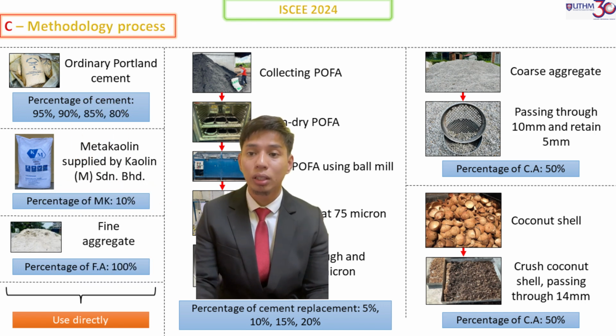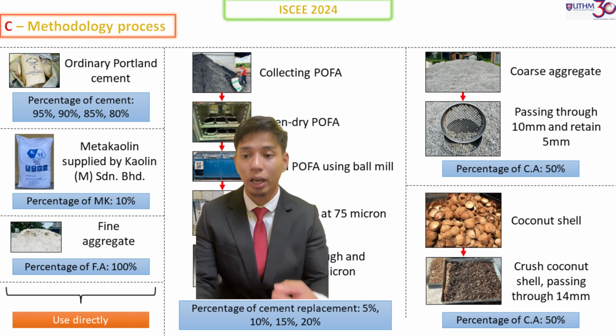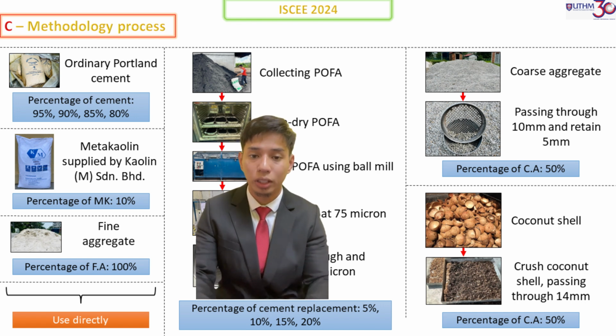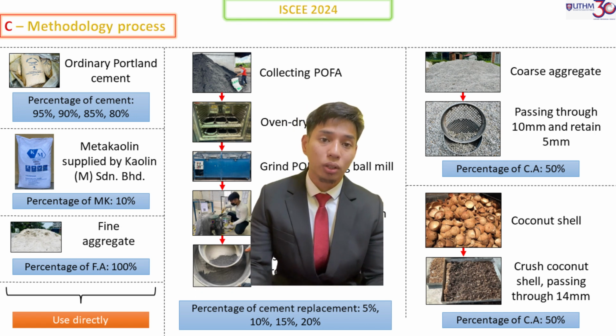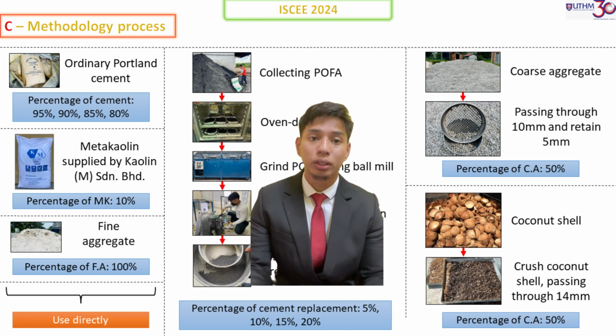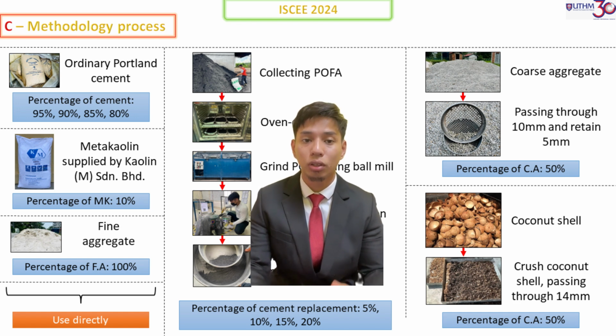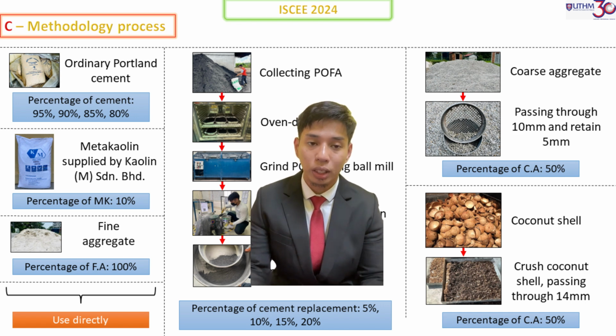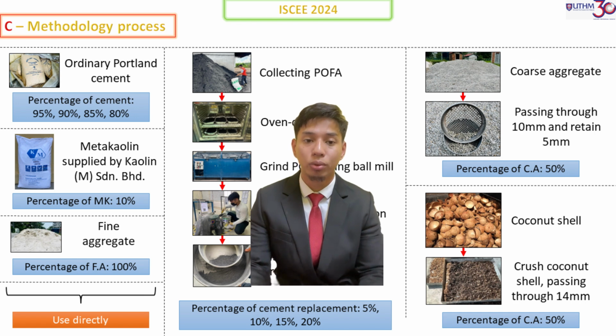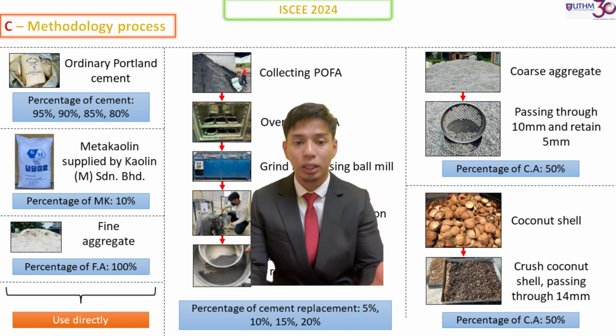For Metakaolin, the percentage of Metakaolin used is 10% fixed. For fine aggregate, 100% is used directly. For coarse aggregate, we go through the process of passing through the 10 mm and retained at 5 mm. The percentage of coarse aggregate used is 50% because the other 50% will be replaced with coconut shell, which is crushed coconut shell passing through the 14 mm.